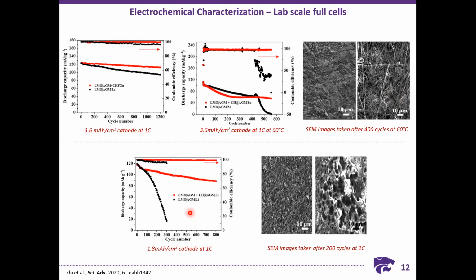So in the case of lithium, the improvement in the battery performance is quite huge when compared to the zinc metal batteries. So here, after like 300 cycles without the use of interlayer, the discharge capacity has declined, while with the use of interlayer, it was actually improved to around 800 cycles, with the capacity decline to around 80%. So with the SEM images taken here too, you can see distinct difference between the one with the use of CH at AGM interlayer and one without the use of interlayer.